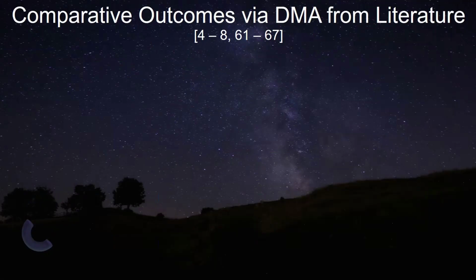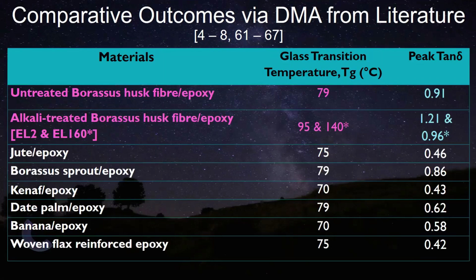Then we tried to compare all those values with the previously found values, and we can see the untreated Borassus fiber epoxy, which is our result, that's why I put it down in a different color, pink: 79 degrees and a damping factor of 0.91. What about the alkali treated Borassus husk fiber epoxy? We used two different resins, and we got 95 and 140 degrees maximum. Similarly, the damping factor was 1.21 and 0.96.